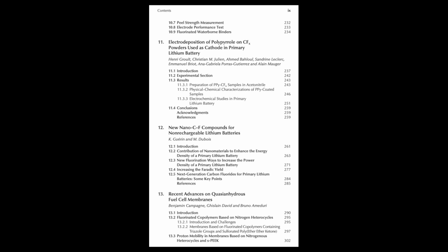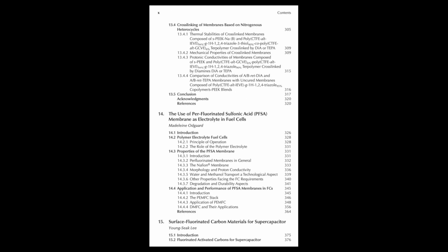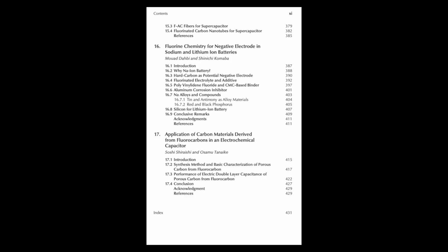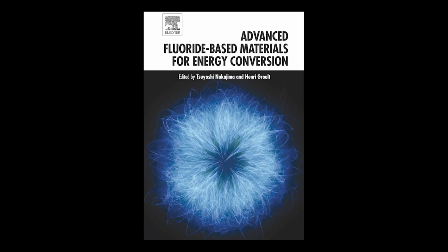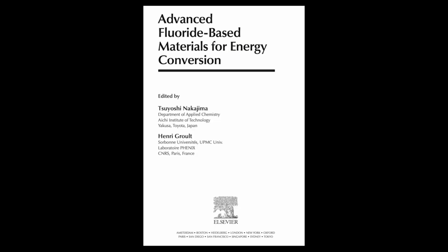The source also touches on an interesting interaction, how the PVDF binder itself can sometimes react with sodium in NIBs, leading to defluorination, losing fluorine, and forming sodium fluoride. That sounds bad. It can be detrimental, yeah. But FEC seems to help mitigate this damage to the binder as well, possibly by forming its protective layer first. Figure 16.10 hinted at that. It sounds like FEC is a really crucial ingredient for making sodium-ion batteries more stable and longer lasting. It's certainly a very important additive being studied, yes.